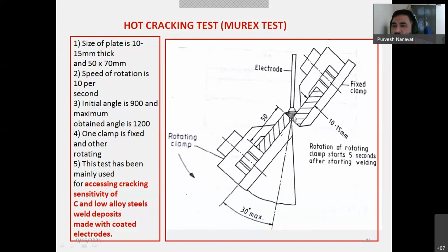Now, having finished this, this clamp is the rotating tab, this clamp is a fixed tab, right? Now, there will be some rotation. Rotation will be limited to 30 degrees maximum. After which a crack will develop in this fillet weld, and this crack will be assessed. And this type of test is done mostly for carbon and low alloy steel weld deposit with coated electrode like SMAW coated electrode.